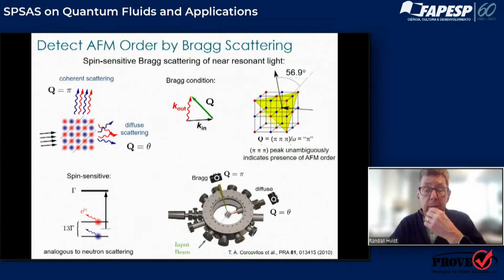And it can be spin sensitive. So it looks a lot like X-ray scattering, except it's actually more like neutron scattering. This neutron scattering is spin sensitive. And we can make this scattering spin sensitive by detuning halfway between what we call the up spin atoms in red and the down spin atoms in blue. So if we're detuned to the red for the blue atoms and to the blue for the red atoms, a little bit confusing, but a more energetic beam for probing the up spins than the down, then one gets a phase shift in the scattering. And that phase shift allows you to distinguish the spin-dependent scattering function.